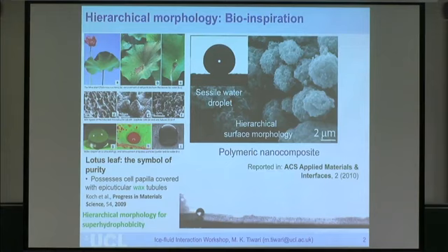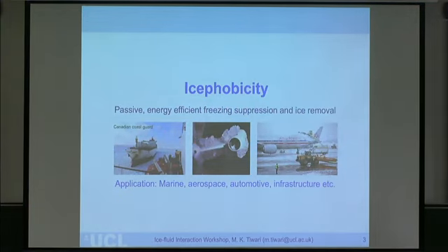Well, the idea, at least at the onset, was to use this liquid repellency so that a droplet can roll off quite easily before it has a chance to freeze, or even if it freezes, it maintains as little contact as possible, so you have low adhesion, and so on and so forth. So that's what leads to this idea of so-called ice phobicity, so surfaces that are repellent to ice, which delay ice formation or have low adhesion.